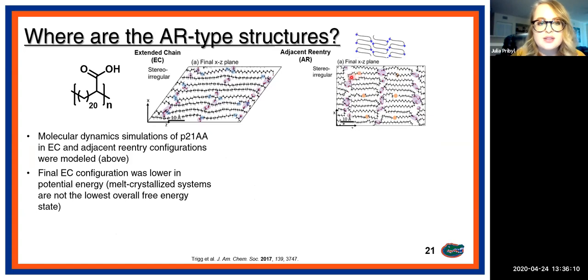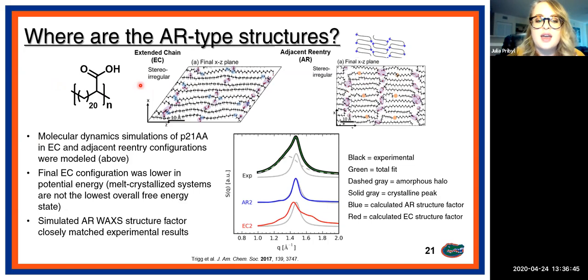So in 2017, they re-examined the polymer that I talked about on the previous slide, and they did some molecular dynamic simulations of this polymer in both an extended chain conformation as well as an adjacent reentry conformation. So the molecular dynamic simulation suggested that the extended chain conformation was lower in potential energy. But they noted that melt crystallized systems are not in the overall lowest free energy state. So more likely they're in a trapped dynamic state. And additionally, they simulated some adjacent reentry wide angle X-ray scattering data and compared it to experimental data.